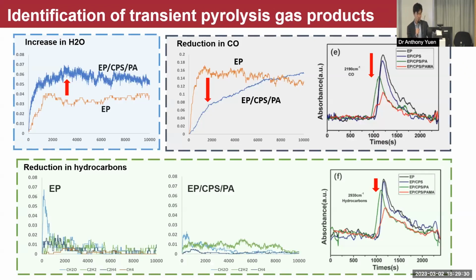Anyway, through our study, we find that even from a numerical simulation perspective, the incorporation of the flame retardant increases the water vapor formation. This contributes to the effect of reducing the chemical reaction that I mentioned in part 4, as well as the capturing of oxygen.